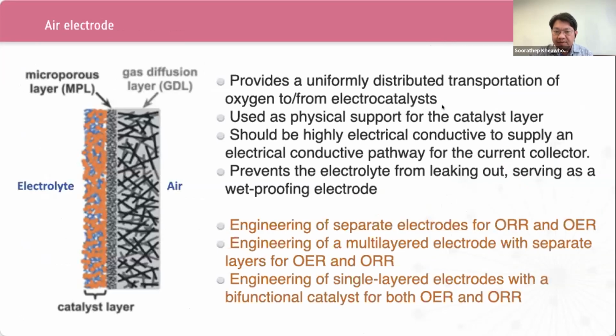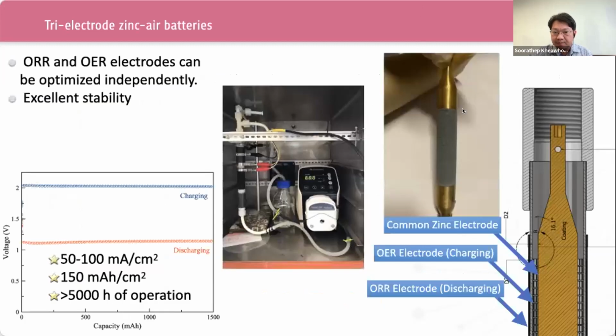Besides the catalyst, the structure of the air electrode is also significant. Generally, the air electrode consists of a gas diffusion layer and a catalyst layer. As ORR is a three-phase reaction, we have to manage hydrophobicity and hydrophilicity of the electrode. Our group is working on a tri-electrode configuration of ZABs. We use separated electrodes for charging and discharging and a common zinc electrode. This system exhibits excellent stability for charge and discharge. Moreover, we can optimize ORR and OER independently. The cell we are currently developing can discharge stably even at 100 milliamp per square centimeter. And now we reach the area capacity of 150 milliamp hour per square centimeter already.